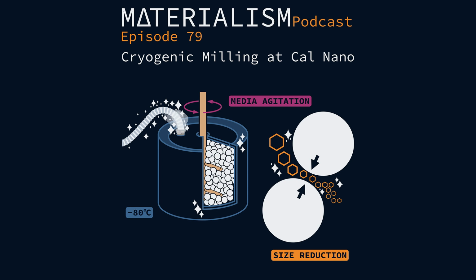So you're going to make them nice and spherical. It does go up in size because you are agglomerating things a little bit. But the point is that you get nice flowing powder, right? These spheres flow nicely, so you get rid of die wall friction. It gets rid of gradients in the density in your pressed ceramic. There's a lot of advantages to it.